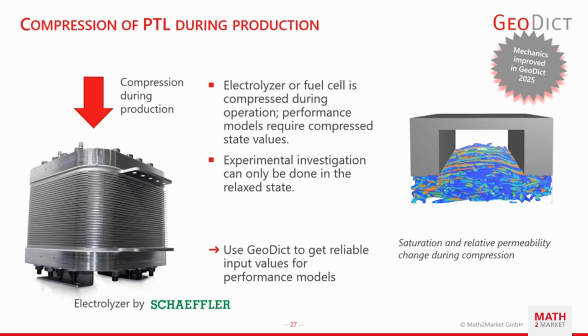And if we want to go into a performance model on a higher scale, we need to enter a permeability value. And the permeability that we get from the relaxed structure is different than the one that we get from a compressed structure, of course. The trouble is if we image the PTL with a scanner, it's usually in a relaxed state. So if you use this image of the relaxed state and calculate the permeability or the diffusivity of the structure and enter this into the performance models, it will probably not be the value that you have during operation. So if you want to have the value that you need for simulating operation conditions, you need to use the compressed structure.